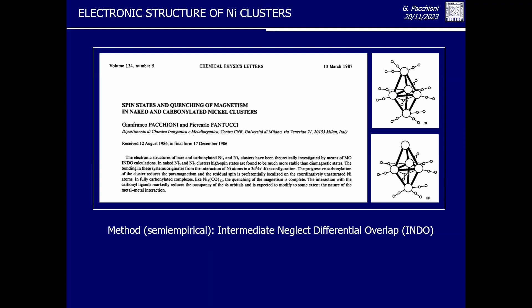We found that CO ligands are not innocent — they change the electronic structure of the nickel atoms and quench the magnetic moment of the nickel particles. If you completely surround a cluster by ligands you can completely kill the magnetization. But these were semi-empirical calculations and we wanted to go beyond that. I got in touch with Notker Rösch in Munich, who was working with density functional theory. At that time very few people were using DFT — it was just starting. With Rösch we addressed clusters with ligands and computed a Ni44 cluster with 48 CO ligands, the largest system computed at that time.